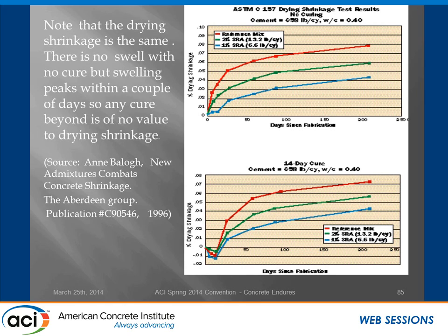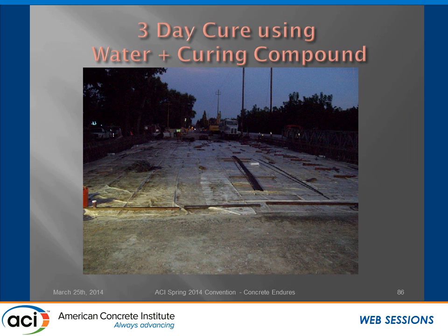Aberdeen Group did some studies with shrinkage-reducing admixture, and the bottom one has a 14-day cure, and the top slides have no cure. And if you slide the top set of curves over to match up with the initial swell, the bottom curve, they're almost the same curves. And so they're basically saying the same thing. After 3 days, you really don't see a lot of impact.